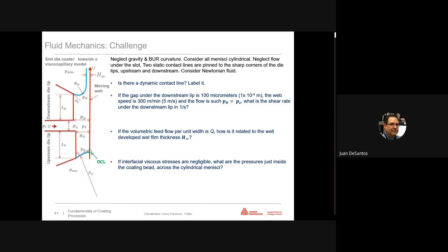I say not far, but in fact, I can tell you that we cut much faster than this. But if you imagine that the gap is 100 micrometers, that is 0.1 millimeters, and you assume that the web speed is 5 meters per second, this is 300 meters per minute, and if for some reason the pressure here is just atmospheric, so that there is no Poiseuille flow, so the flow is purely Couette with these assumptions, it is asking you, well, under these assumptions, what is the shear rate? And you will find, if you make the calculations, that in those conditions, the shear rate is 50,000 reciprocal seconds.